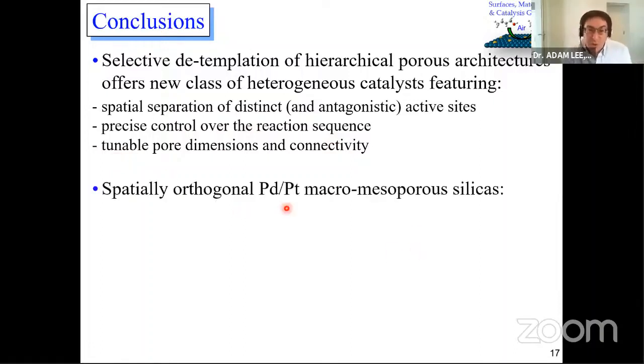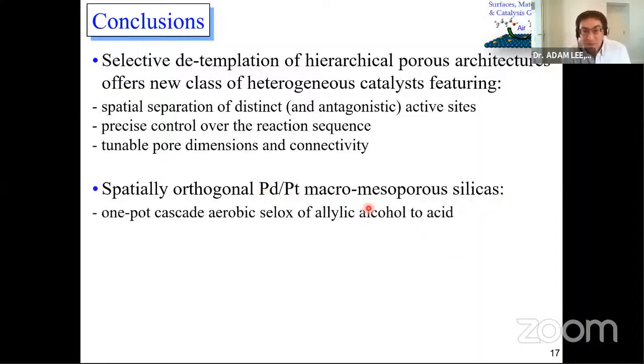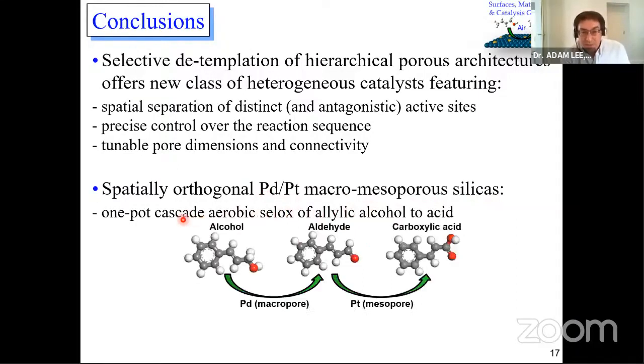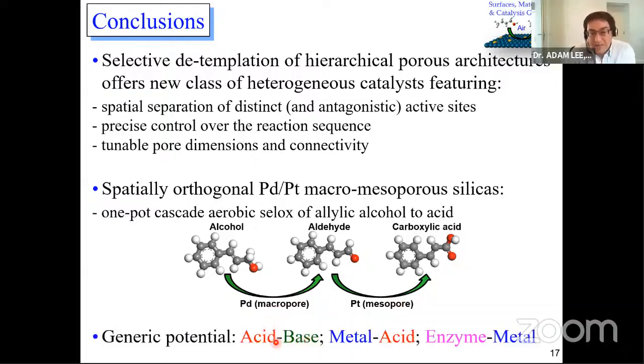The two examples I've shown you are for a palladium platinum meso-macrosilica, where we drove a one-pot cascade oxidation, where we took an alcohol, we oxidized that first over palladium to an aldehyde, and then we oxidized the aldehyde over platinum to an acid. And we did that using the metals in 2 different pores. I've also shown you the acid and base approach, where we can do, for example, biofuel synthesis or fine chemistry. And because the pores are so big, because these macropores are hundreds of nanometers, you can even imagine putting an enzyme in one of the pores and putting a metal or an oxide catalyst into the smaller pores. So you could do tandem chemo-biocatalysis now.